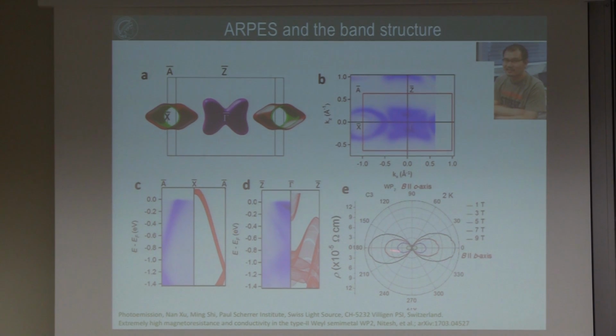And you see the magnetoresistance effect. This is a magnetoresistance effect in the plane. It's very anisotropic along the B axis in our material, consistent in some sense with a very anisotropic electronic structure.